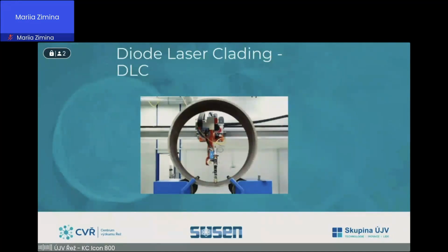And the last technology I would like to say something about is diode laser cladding. Laser cladding is a deposit overlay technology which uses a high power industrial laser to melt or weld material into a substrate, creating an overlay with true metallurgical bonding. Laser cladding is a very competitive alternative to traditional arc-based cladding methods. Due to much lower heat input, the technology can be used for cladding large surface areas, and can also be expanded to applications like repair or additive manufacturing.